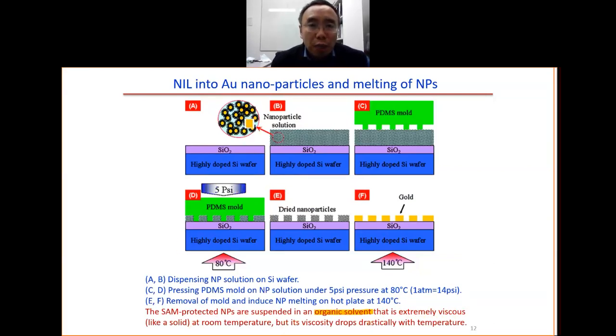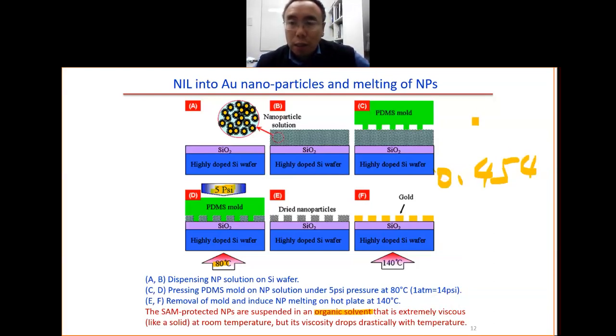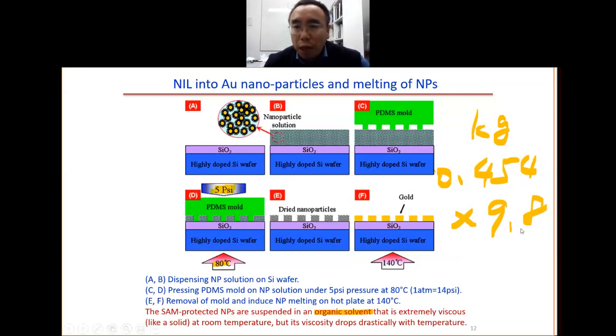So you dissolve the nanoparticles in the solvent. You have this soft PDMS mold, a flexible soft mold. You heat up to 80 degrees and apply a little bit of pressure, 5 psi. The psi is pounds per square inch. Each pound is about 0.45 kilogram, times 9.8, which gives you the force in newtons. One atmosphere is 14 pounds per square inch. So here you have 5 psi. Then you have the pattern in this solvent. You dry away the solvent, leaving behind the dried nanoparticles. Then you heat up at 140 degrees. The nanoparticles get merged together, and you get the gold film, the gold pattern.